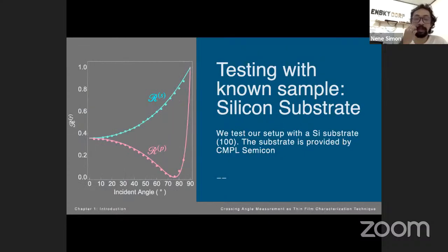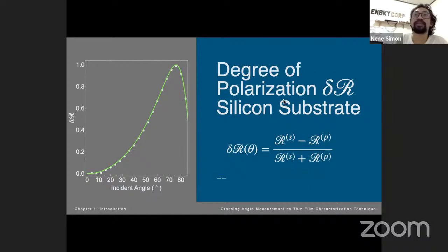We also test our setup with a standard silicon substrate. The plot here gives you the reflectivity of a silicon substrate. And I'd like to take this opportunity to thank Condensed Matter Physics Laboratory Semicon for providing us a bare silicon substrate. Out of the data points here, we can calculate the degree of polarization of the reflected light, delta R. Delta R is equal to Rs minus Rp all over Rs plus Rp.